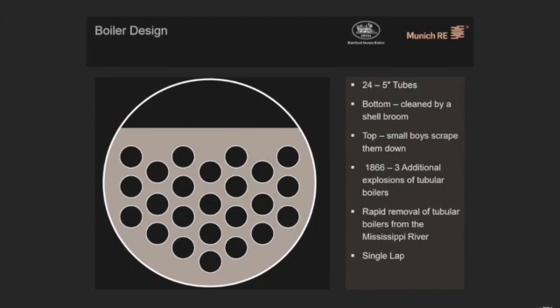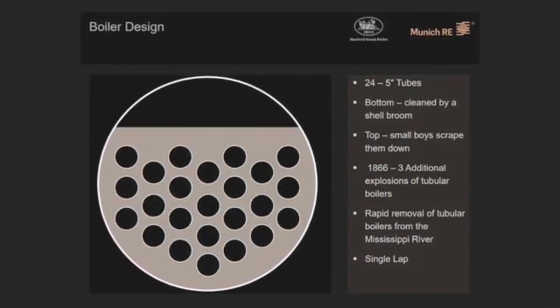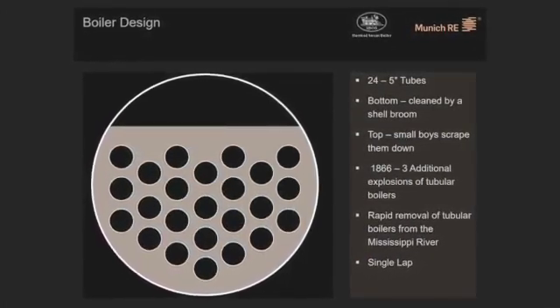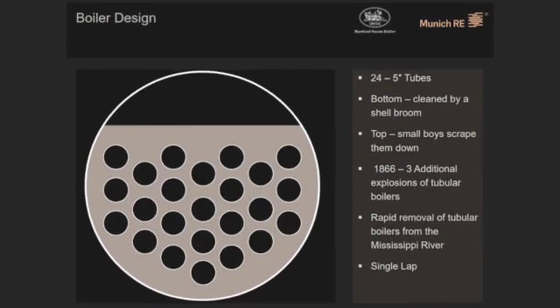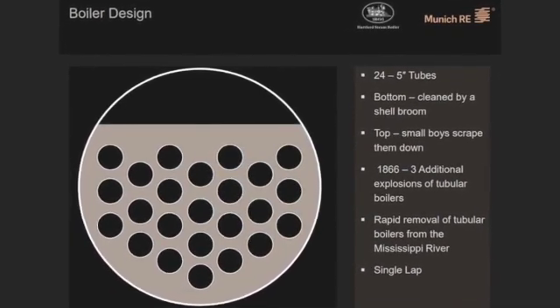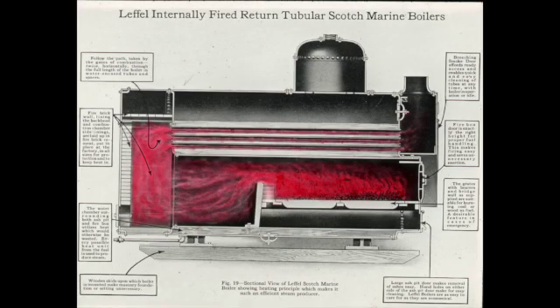A severe combination of factors led to the failure of the Sultana. The first can be traced back to the faulty repair of the boiler. The material of the boiler was charcoal hammered No. 1 iron, a metal that was exposed to prolonged heating and cooling, which will harden and become brittle.